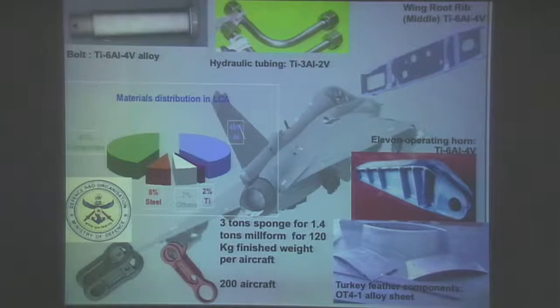So here's a variety of products developed through similar manufacturing routes that are used in the light combat aircraft. Currently, a program is on to establish titanium undercarriage components to replace steel. But I do want to point out to you that for every 120 kilograms of finished weight per aircraft, you actually use 3 tons of sponge. That is the buy-to-fly ratio of titanium, because of its extraordinary affinity for oxygen and therefore the loss of material as you start from the titanium raw material to the final part that you see over here.